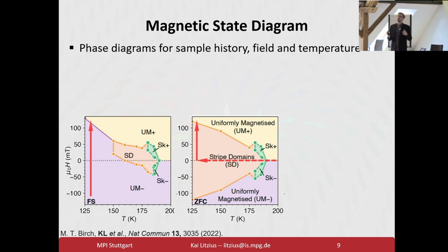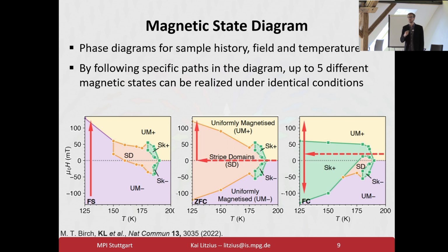There's, however, also different histories that we can apply. For example, we can do a zero field cooling, where we go through TC from high temperatures, go down, and then sweep the field up and down from the center position. Of course, you end up with a symmetric phase diagram this time, but you end up with a much, much larger stripe domain phase. So you can extend the phase where you can get stripe domains quite easily by just cooling through TC at zero field. You can also do this cooling, but in field. And now you don't extend the stripe domain phase, but this time you extend the skyrmion phase. So in this case, we cool at 20 millitesla and sweep the field up and down. And here we get a very extensive skyrmion pocket.